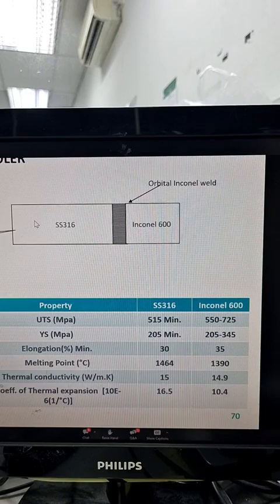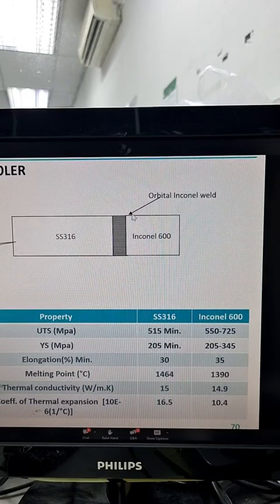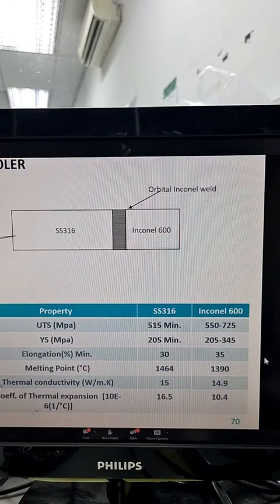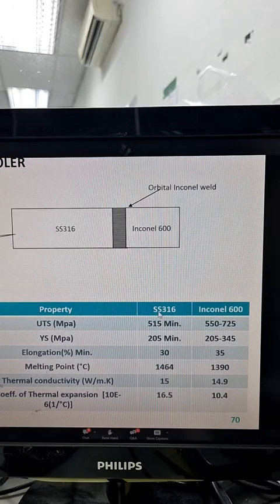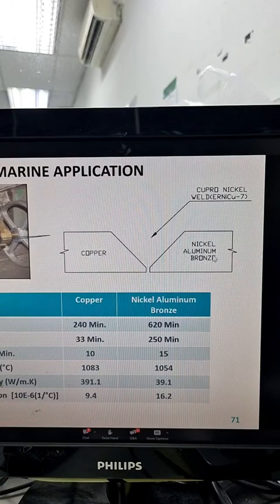Another combination is a tube to tube joint in a reactor where you weld stainless steel to Inconel 600. Here there is a requirement of producing these welds defect free with the orbital welding technique, because what you require is a totally defect free joint as the service is highly critical.